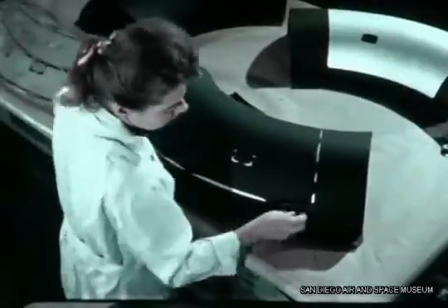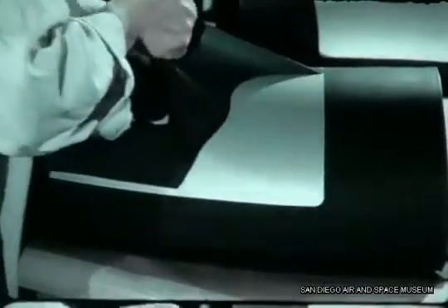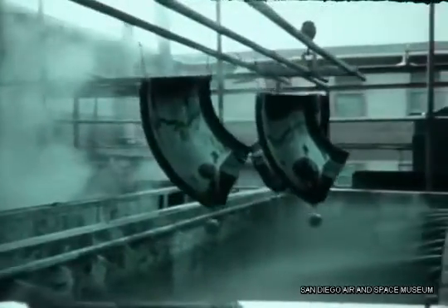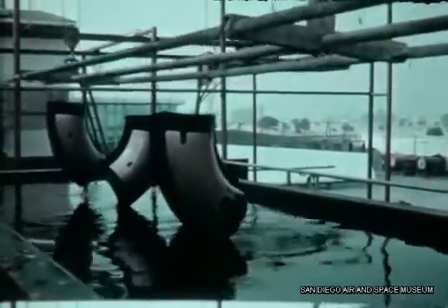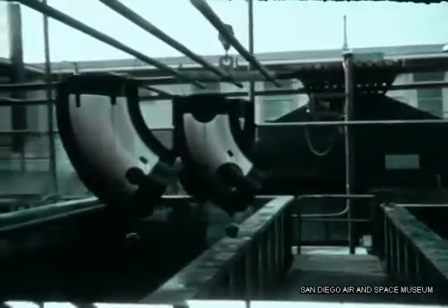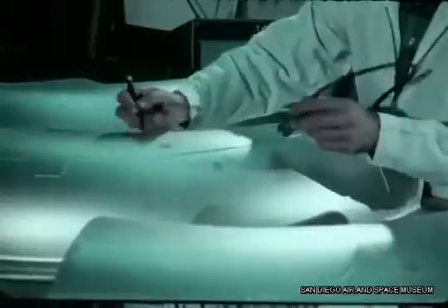The formed tank segments then went to Chemtronics near San Diego for chem milling. A neoprene resin coating on the parts acted as a selective etching mask. The areas to be milled were outlined and the neoprene mask removed. A sodium hydroxide solution etched the exposed areas, accurately milling the parts to specified tolerances within five one-thousandths of an inch. Chem milling allows for varying thicknesses in the tank walls where needed — the areas near the butt weld can remain thick to reduce the stress level at the weld, while other areas are reduced in gauge to remove excess weight. When completed, the pieces, originally 63 thousandths in thickness, measured 25 thousandths in the thinnest walls and 50 thousandths in the thicker weld areas.